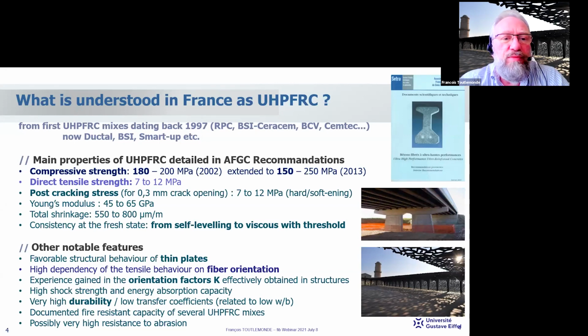The main properties have been detailed in the first recommendations by the French AFGC, the French Association for Civil Engineering, which is the French branch of FIB. The compressive strength was around 180 to 200 megapascal, as given in the recommendations edited in 2002, and extended to 150 to 250 megapascal.